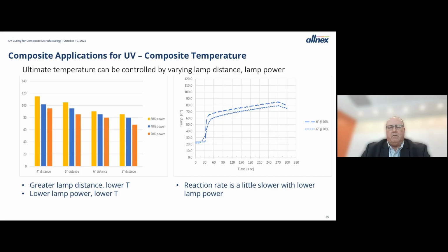Now, the slight downside is that the reaction rate is a little bit slower, and that's part of the reason the temperature doesn't get so high. It still reaches complete cure, but it does so over a slightly longer period of time. And so the reaction rate is a little slower, but your peak temperature is lower, and you just need to run a little bit longer. And we're talking maybe an extra minute or two. So still a very fast process, just not as rapid as it could be if, as I've said, you need to control the temperature of your system.